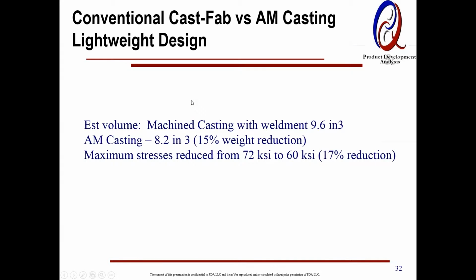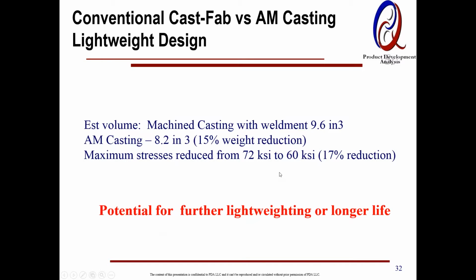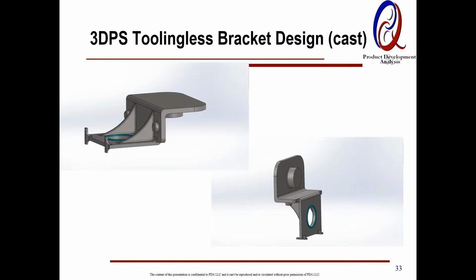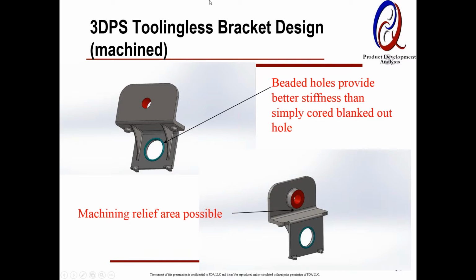So here is the casting, here is the welded plate with the braces, and here are FEA-based predicted stresses. Here is the loading. There's a bearing which goes in, and this is how it is made currently. What we did is we went with the additive route using 3D printed sand and gained about 15% weight reduction, and reduced the maximum stresses from 72 KSI to 60 KSI. So there is potential for further lightweighting, or because this is highly fatigued, with lower stresses you will see a longer life of these components. It's high cycle fatigue. So this is the bracket design we came up with.